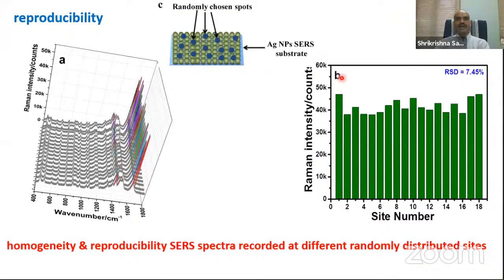This is very important. This is another point which we have to have for the Raman signal: reproducibility. If you have this Raman SERS substrate, if I put the dot here, here, here, at random positions, and if you see the Raman intensity is more or less the same, then we say that it is a reproducible Raman signal. So if you are going to make this SERS substrate, means you are going to grow these metal nanoparticles, one factor you have to see is that it should be homogeneous and reproducible at different spots.